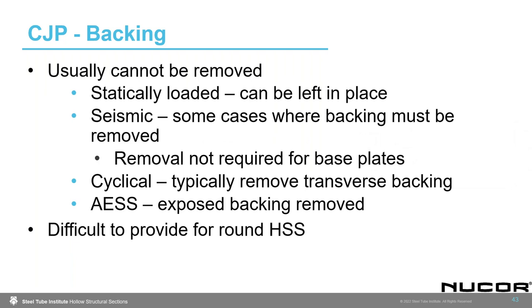As you know, backing can't be removed. Once it's in there after we've performed a weld, we can't really get in there to get it out. So mostly that's okay for statically loaded structures. In seismic, there are some cases where the backing must be removed. However, base plates is not one of them. You do not have to remove backing for base plates for seismically loaded HSS.